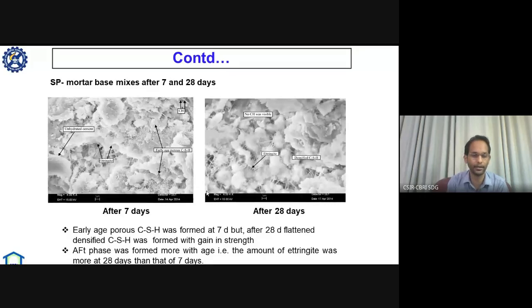The formation of ettringite will take place again, and apart from AFT, there will be formation of two other kinds of phases. That is AFMC, that is monocarboaluminate, and hemicarboaluminate. Although the solubility product of calcium carbonate is quite low, it is like if you add 100 gram of calcium carbonate, then only 20% of calcium carbonate will dissolve and take part in the reaction. So the formation of hemicarbonate and the AFMC phase will be there, which stabilize the AFT phase, as you can see in the right part.